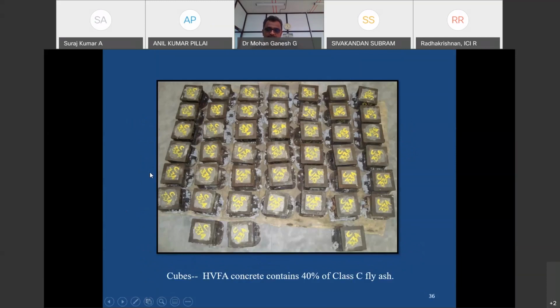Now, either the IS code or the Euro code, for finding the strength, always says a minimum of 3 cubes we have to test at 7 day as well as 28 day. For M30 grade, that is the process. After 28 days of curing, we do the compressive strength test. But for this project, since we went with different percentages, we cast nearly 50 plus cubes in a single casting. This picture shows the complete view of one set of casting.